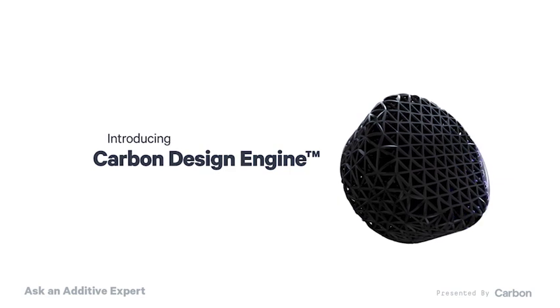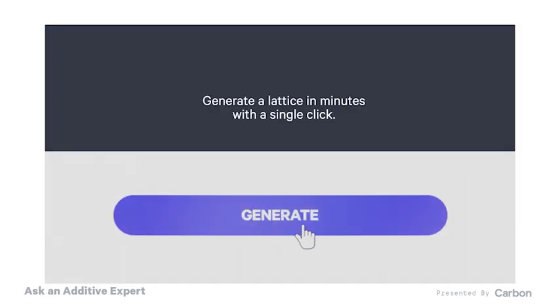The easiest solution is to communicate with the customer and find an appropriate lattice that might help reduce the thickness of that cross section, which will lead to a cheaper part but also one that's going to perform much better. There are problems with printing large volumes on many different 3D printing processes — for resin printing, it can be difficult to refresh the resin across a large piece. With thermal 3D printing processes, heat builds up in the part, creating residual stress and leading to warping. Fortunately, it's become a lot easier to add lattices to your part recently. Carbon just released the Carbon Design Engine software that makes it easy to do that.